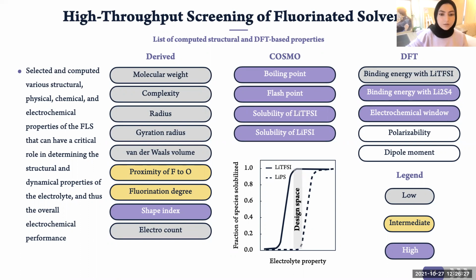The third group are DFT properties, which are more expensive calculations than the first 2 groups, and they include the electrochemical window, which determines the voltage range within which a battery can operate, the binding energy of the solvent with both the salt and the polysulfide species. And these 2 properties determine the affinity of the solvent towards the electrolyte components. And finally, we have some electronic properties like the polarizability and dipole moment. And using all of these predicted properties, we can determine the region in the design space that results in the optimal solubility of the lithium polysulfide species.